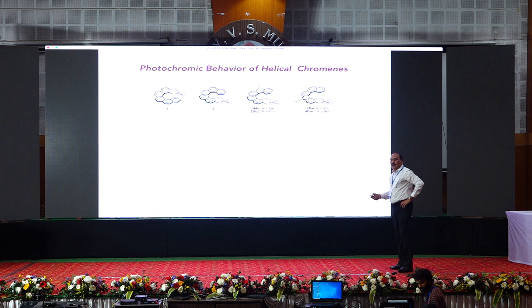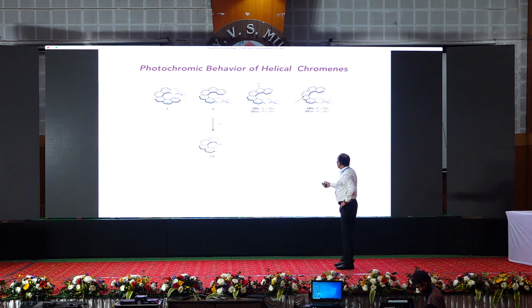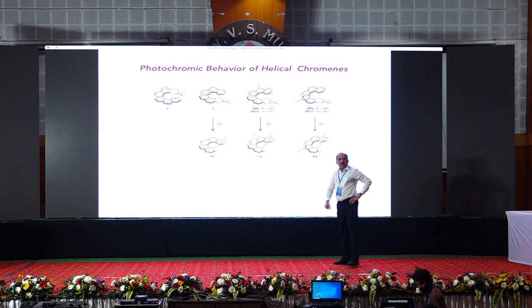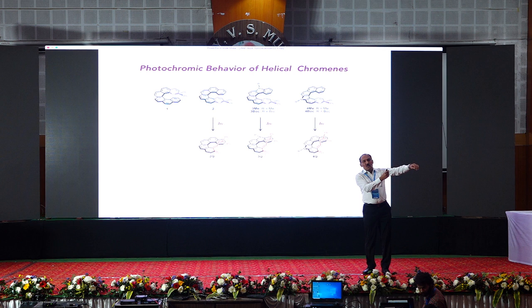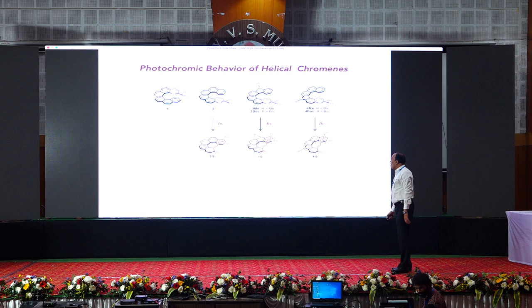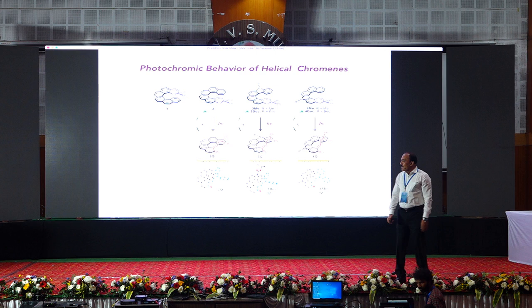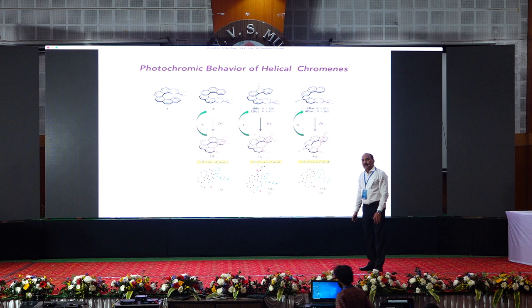We designed a series of molecules, and they're all helical, and here are the systems. That is a molecule that I talked about, right? And now let us have systems like this. So I put a five-membered ring there, I put a five-membered ring here. By putting a five-membered ring even before the helical turn takes off, you see that the helical scaffold moves away. So hindrance becomes lesser. In fact, as presupposed, all of these molecules are stable when you shine light, colored forms, but the colored forms now go back to colorless forms with different activation barriers. And this is the activation barrier that we had to begin with, around 30.